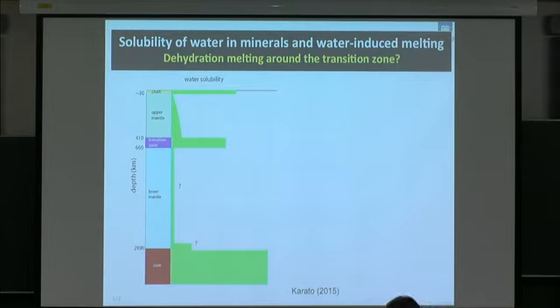And this distinct solubility profile causes plausible melting due to the vertical material motion. Imagine if you have a material moving from deep to up through the transition zone, and if the materials have a relatively large amount of water, the material is going to be happy and no melting in the transition zone because solubility is so high. But as soon as these materials go up to the upper mantle, solubility is so low, and therefore melting starts.